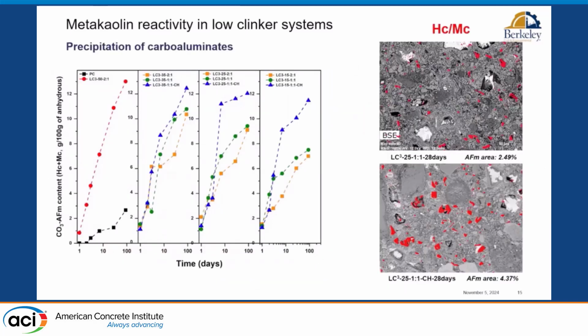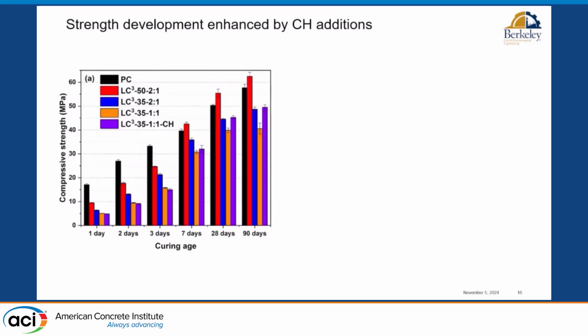And why do we want to sustain the pozzolanic reaction in these low clinker LC3s? Because sustaining it means that we keep precipitating these key phases, carboaluminates, in order to fill these big capillary pores that we have in the microstructure and therefore increase the strength. So if this all connects, we would expect to see an effect of these calcium hydroxide additions in the compressive strength, right? Well, in LC350, we do not see an effect because LC350 is a system that is not limited by lime availability, at least not when kinetics are considered.